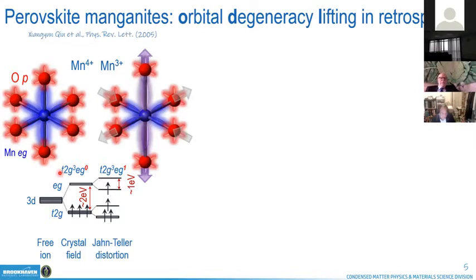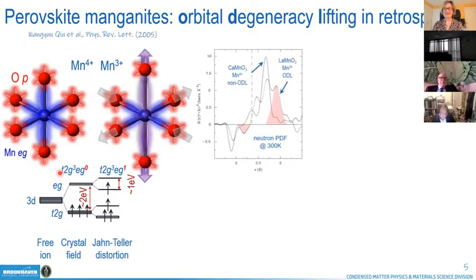Now, this lattice distortion is pretty strong, and of course, since it's a lattice distortion, you can sense it in the structure. And so this is a materialization of 3+ and 4+ manganese states in 113 manganites, calcium and lanthanum versions. And you can see that when manganese is 3+, meaning when it has 4 electrons in the d manifold, you do have a distortion. This is a neutron PDF. And when you remove that electron, that's the calcium variant, basically the distortion goes away.